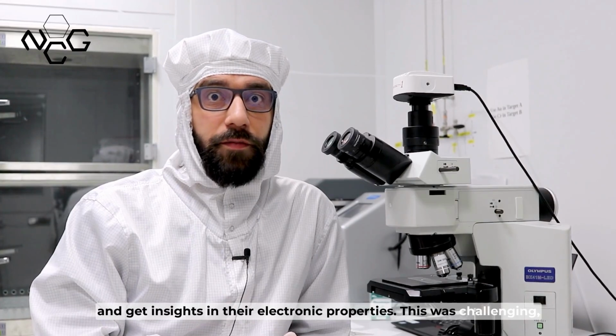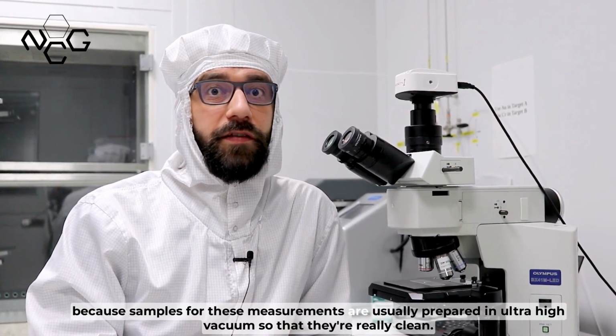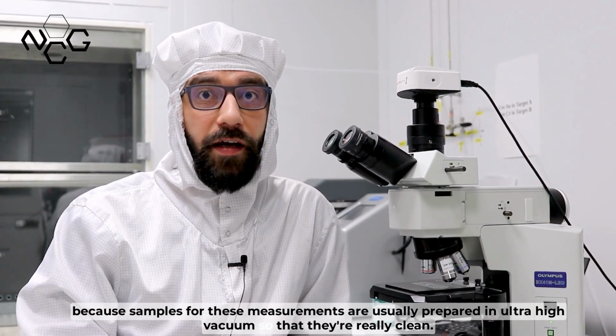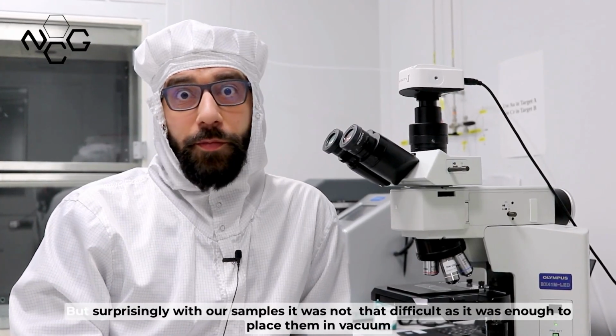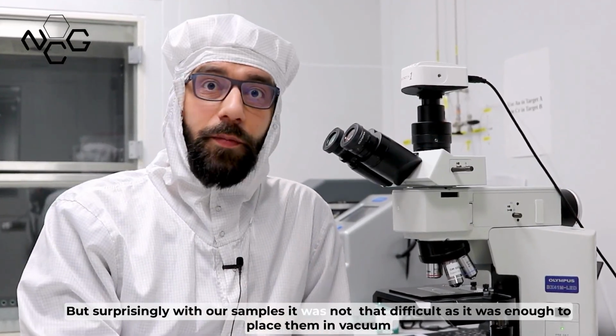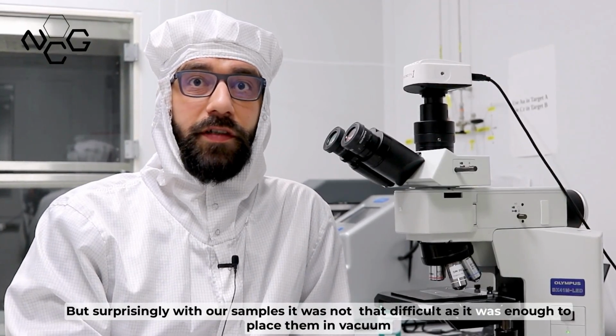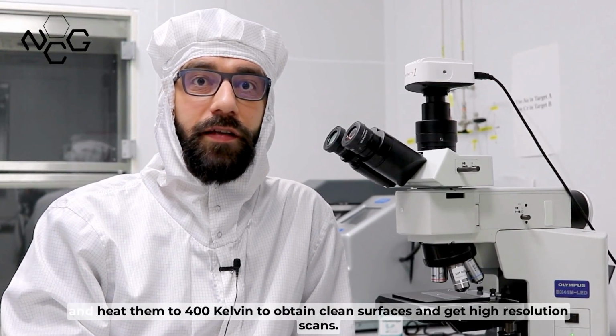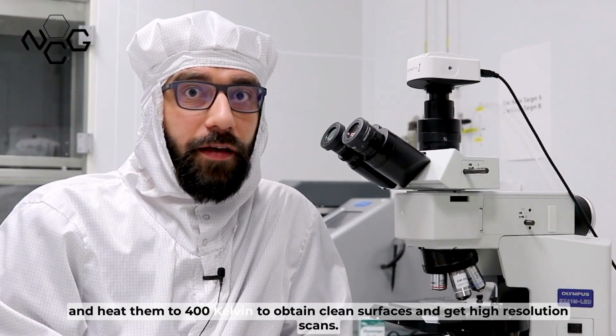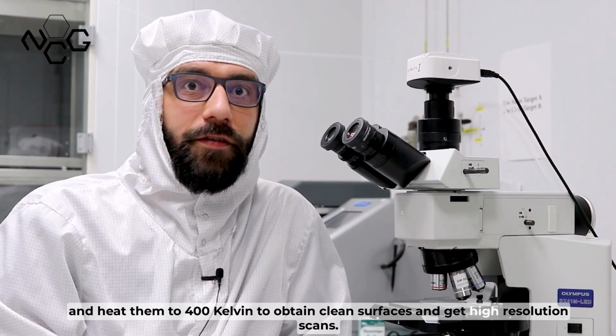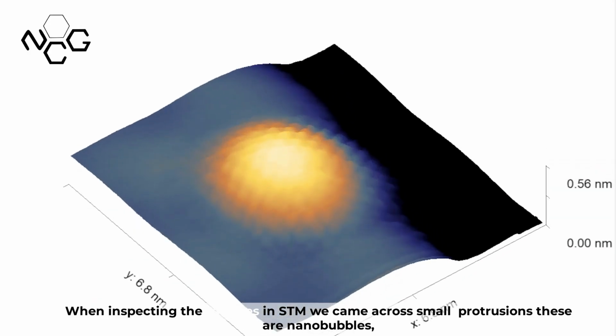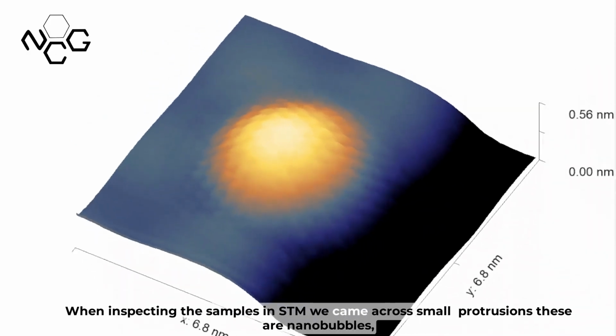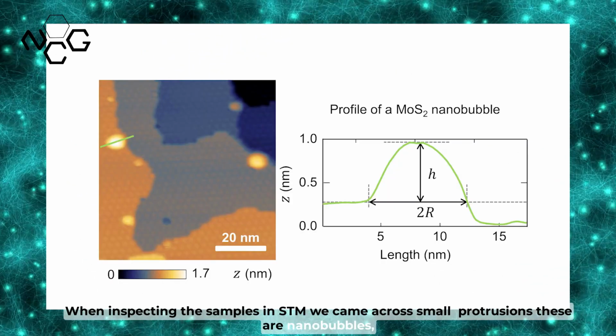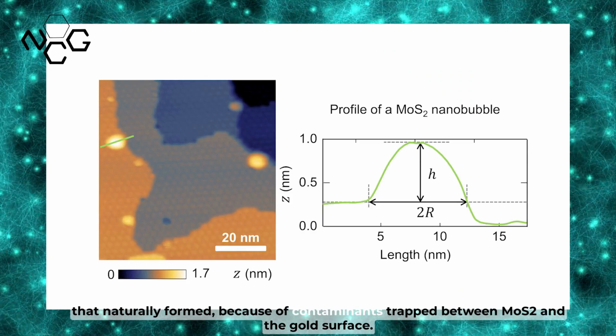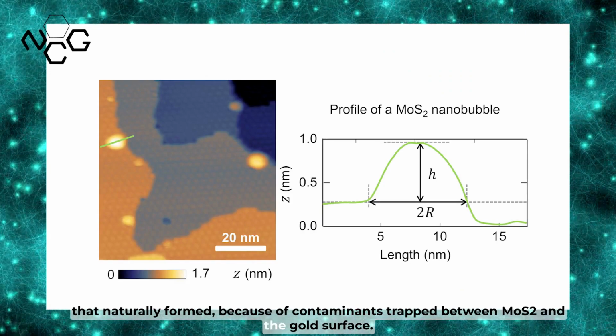This was challenging because samples for these measurements are usually prepared in ultra-high vacuum, so that they are really clean. But surprisingly, with our samples, it was not that difficult, as it was enough to place them in vacuum and heat them to 400 Kelvin to obtain clean surfaces and get high-resolution scans. When inspecting the samples in STM, we came across small protrusions. These are nanobubbles that naturally form because of contaminants trapped between MoS2 and the gold surface.